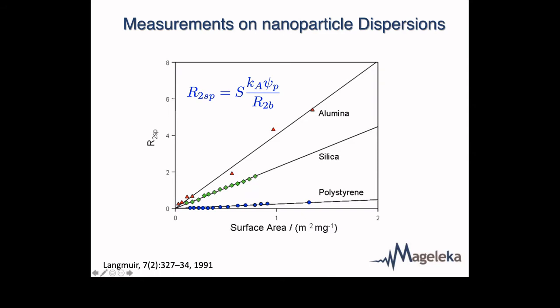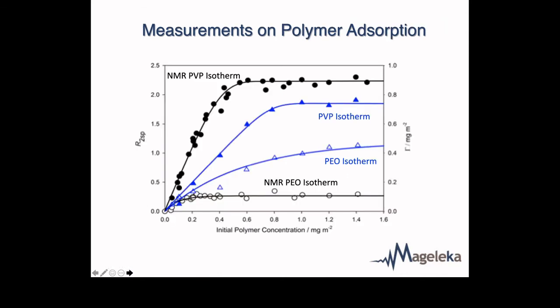Polystyrene latex is basically a hydrophobic surface. So the interaction of water with a hydrophobic surface, well, partly hydrophobic surface, it does have sulfonate groups on, is much weaker. So you can see the slope of these curves tell us something about the surface energy, the interaction between the water and the interface. This sort of thing would be very hard to get some idea of without doing a complicated calorimetry experiment. It's quite difficult. And these experiments, they take minutes to do. So this is a nice application.